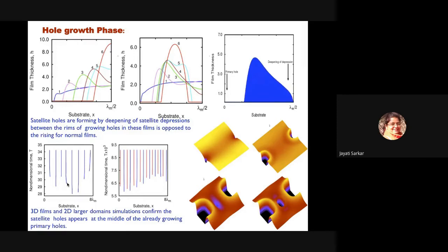What happens differently in this case is that the fluid, instead of leveling out, at these thicknesses, when the thickness of this region in front of the hole is very small, the van der Waals interaction is again very high, because the mobility is very high in the lower region, because the viscosity is very low over here. So this helps the film come in contact with the surface once more, right?